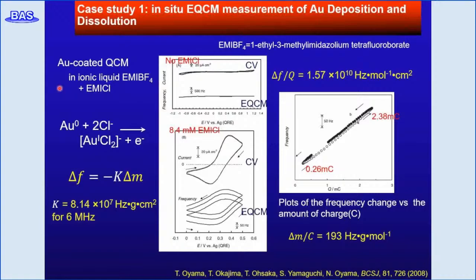However, when EMI chloride is added in EMI-BF4, the CV and EQCM response was observed as shown here. This CV peak at 0.25 volt versus Ag/QRE arises from the electrochemical oxidation of the Au surface to form an AuCl2 complex, which is very stable and shows a reversible voltammogram response of the Au(I)/Au(0) couple.